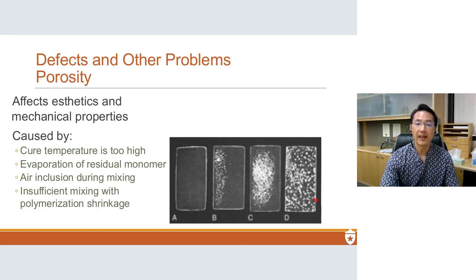The next figure here shows you what happens when air is included during mixing. So there wasn't enough pressure built up to squeeze out the air bubbles. And those are much larger bubbles, as you can see. Or if you don't mix it enough and you get polymerization uneven throughout the material, so you have more shrinkage on one side, less on the other, and that can form porosity as well.